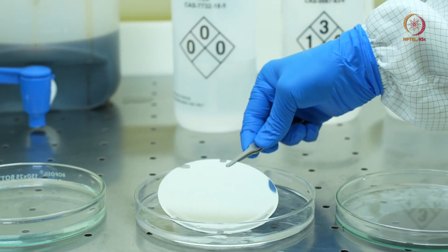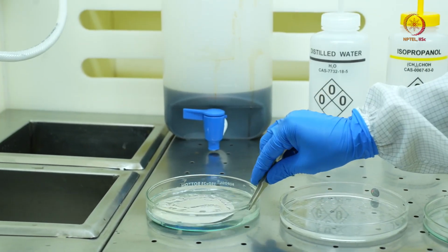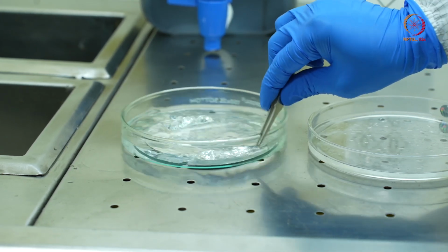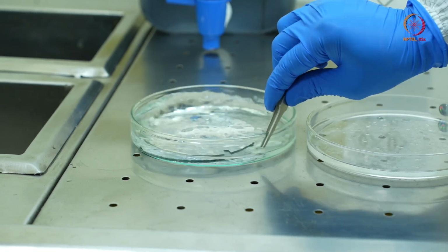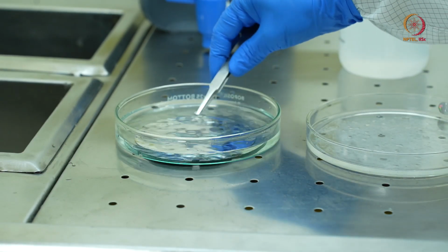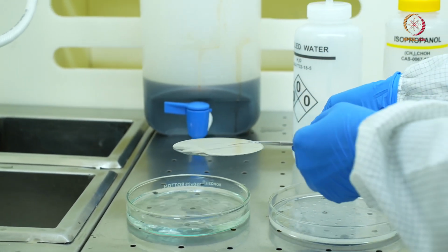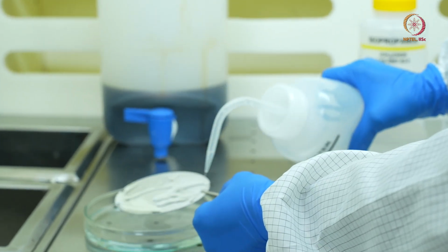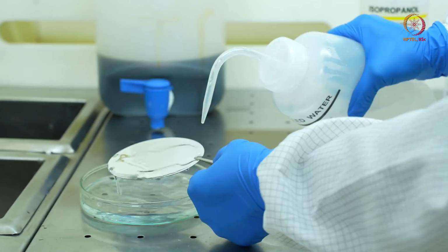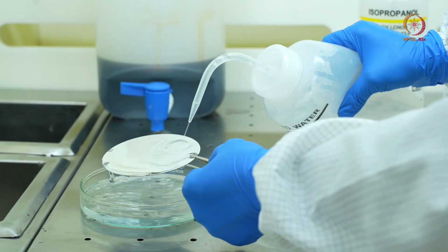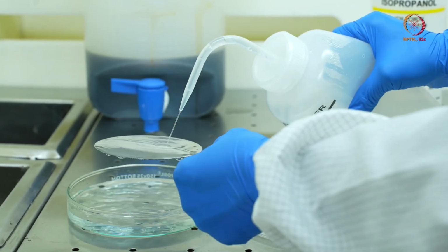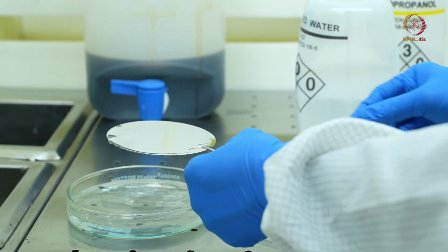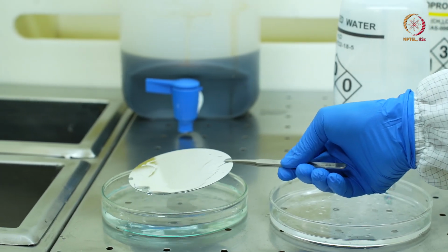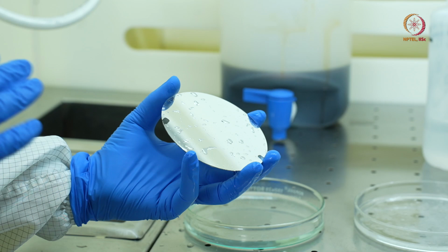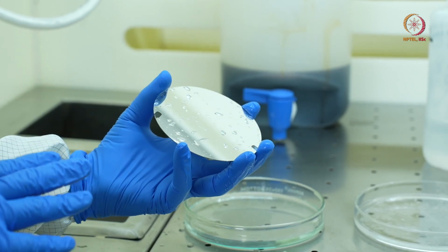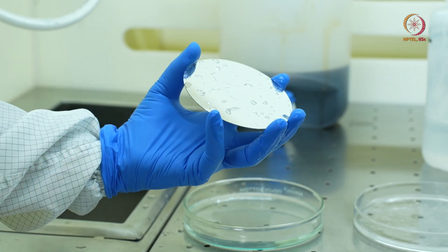Now 2 minutes are over. We will move from IPA to DI water and keep on agitating it for 1 minute, and then we will wash it off again. After washing it for some time in DI water, I'll take it out and wash it with running DI water. This ensures that any residual IPA or acetone on my sample is completely washed away. Once that is done, I will be blow drying it with nitrogen. Now after washing my sample with DI water, I have ensured that there are no traces of acetone and IPA. Now I'll blow dry with nitrogen.